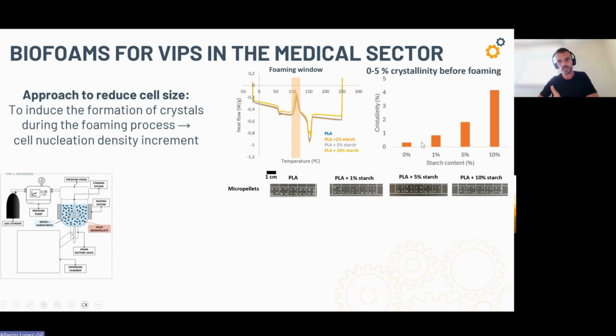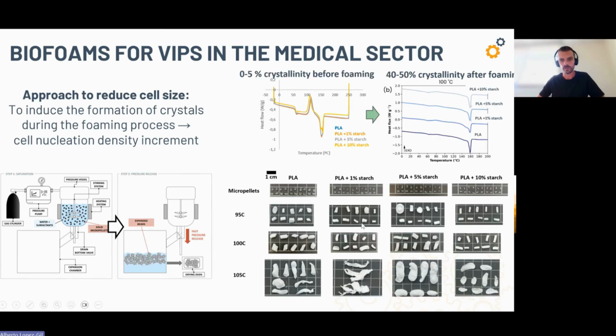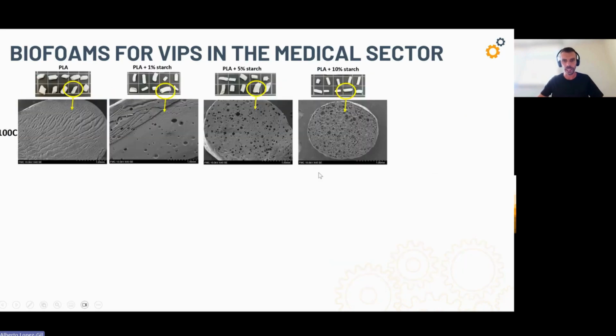You already see that we could increase crystallinity by having starch in the formulation. But what we observe when we foam the different formulations at 3 different temperatures within this range, below the melting temperature of PLA, is that we were increasing the crystallinity of the PLA. And this is occurring at the moment when we open the valve and the polymer expands. So when the polymer expands, there are a lot of crystals in the polymer, and these crystals are inducing the formation of many cells in the foam. And this increment in the cell nucleation allows us to reduce the cell size a lot.